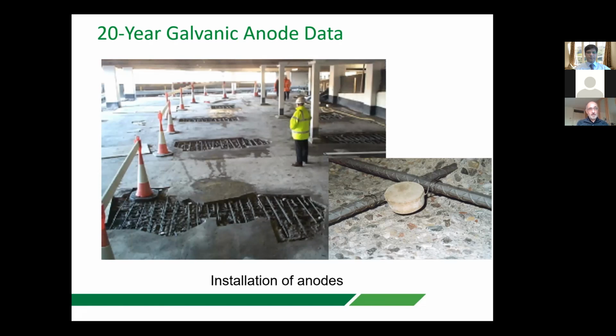It's now called the ring effect. It's been known for many, many years. And our solution was to attach this type of anodes around the periphery in order to maintain that region inside the patch repair as anodic. So the anodic areas are now these little anodes. They're the corroding bits that are corroding sacrificially, and they protect the surrounding region, particularly the periphery of the patch repair.